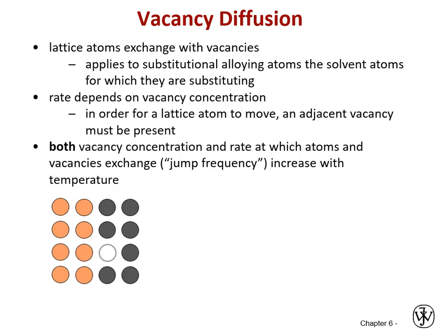So if you remember back to our previous discussion about different types of solutes, you can have a solid solution alloy exist either on a lattice point of another material, where it's substituting for that on the lattice points, and again we use copper nickel for that argument, or you can have your solute atom fit into the crystallographic interstitial positions like carbon does in iron. So the idea of vacancy diffusion is very important for your substitutional solutes that need to diffuse.